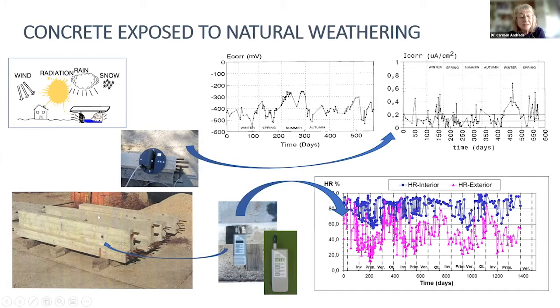We did big elements, and we made some holes in the elements, and we were measuring the relative humidity. We call it the internal relative humidity, because we measure inside the concrete, of course in a small cavity, but in any case not in the atmosphere but inside the concrete. We were measuring the corrosion rate with our portable corrosion rate meter, and we were following the potential and the corrosion rate, and we realized that it changes very much with the climate, with external conditions. And we were trying to analyze this further.